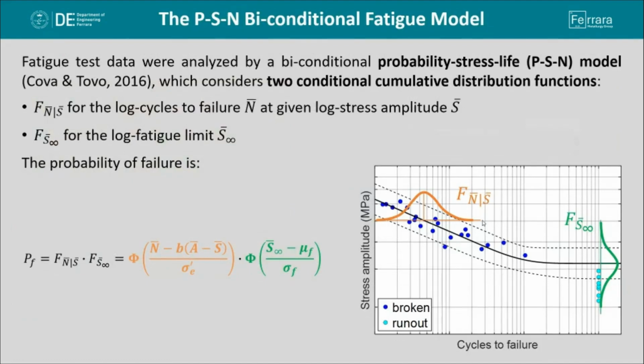The fatigue test data were analyzed by means of a biconditional probability stress-life model, which was taken from the literature and is similar to other ones present in the literature. This specific model, going briefly into the detail, considers both the finite life region of the S-N curve and the infinite life region by means of two conditional cumulative distribution functions, which are the orange one and the green one.